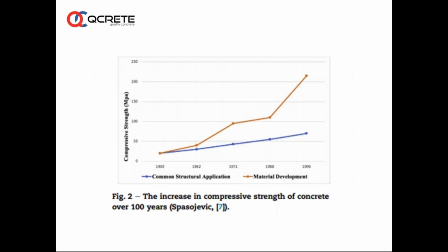Now, we can see from this graph, over a period of time, in the last 100 years, concretes started with a low strength. You can see the concretes in the 1900s used to be around 20 or below, and then slowly the strengths have gone up due to evolution, research and improvement in materials, inventions such as superplasticizers, hyperplasticizers, supplementary cementitious materials, etc. The strengths have shot up, and we can produce 200 or more than 200, but the common applications are in this zone represented by this blue line.